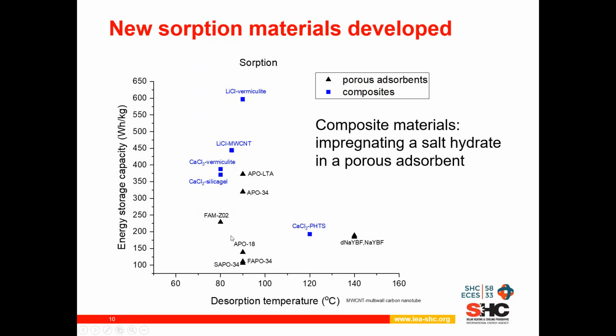The black triangles show the performance of these sorption materials in this application for the pure sorption materials. And the new development now is that to these sorption materials, other materials are being added, salt hydrates, and this leads to a composite material that has better performance. You see this in the performance of the materials with the blue squares, and especially this lithium chloride impregnated in vermiculite material. It has a double performance of the average of the sorption materials. So this is an important development within the subtask on materials.